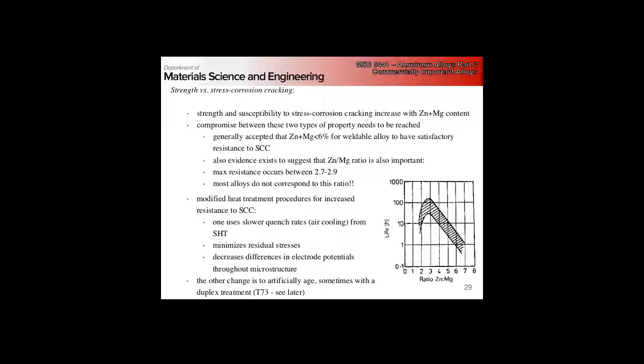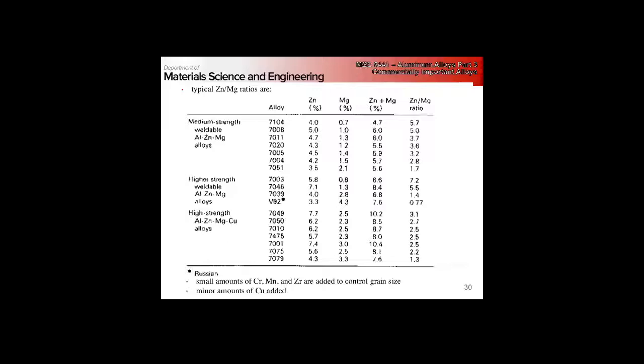So a lot of these we have to go through a modified heat treatment, slower quench rate, air cooling basically. This minimizes our residual stress. We also, because we're not nucleating so many things or segregating, basically reduce our internal electrode potential differences between all the little particles in there. So we have slightly better corrosion. And then typically this will be artificially aged.